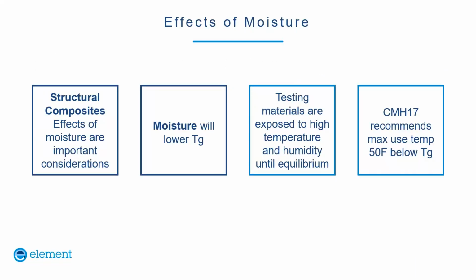For structural composites, the effects of moisture are very important to consider. Moisture will plasticize the material and make it easier for polymer chains to slide over each other, and it thus lowers the TG. So for mechanical testing of composites, we generally expose samples to high temperature and humidity until equilibrium, and they're weighed several times a week until they no longer gain weight. This whole process can take several months, so it's usually a qualification test.